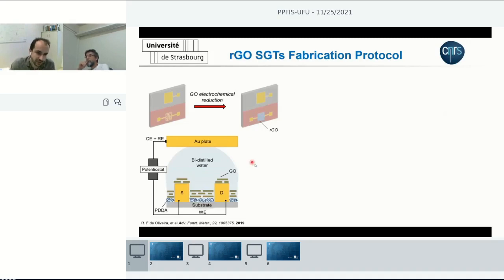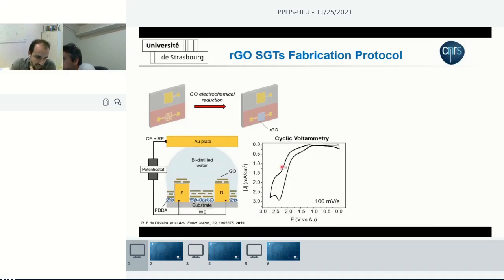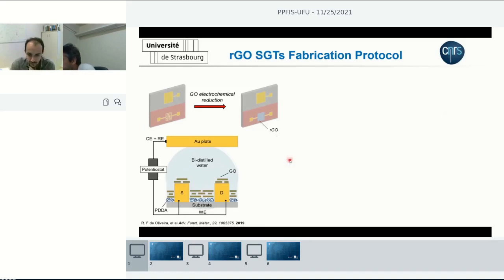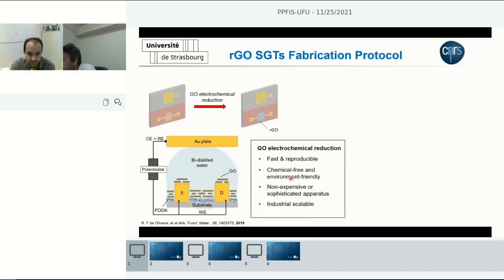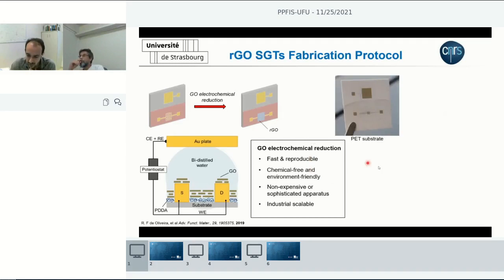And in this case here, we reduce the graphene oxide via electrochemical method. So we use a potentiostat, where we have our substrate with source and drain electrodes, the adhesive polymer film, the graphene oxide flakes. We put a drop of water sitting on top of the film. We close the circuit with a gold electrode, and we perform a few scans of cyclic voltammetry to reduce graphene oxide, transforming it into reduced graphene oxide. Again, the advantages are this method is fast, reproducible. In this case, we use water, so it's free of any solvent or aggressive chemicals, so it makes our fabrication an environment friendly method. It's non-expensive as well and scalable.